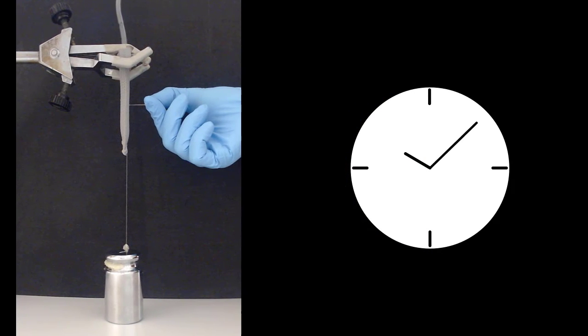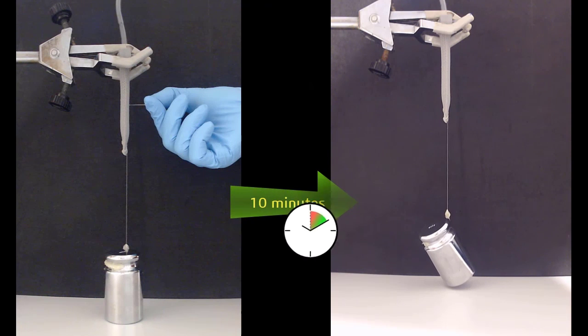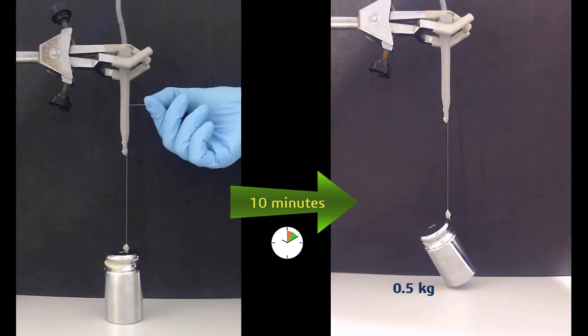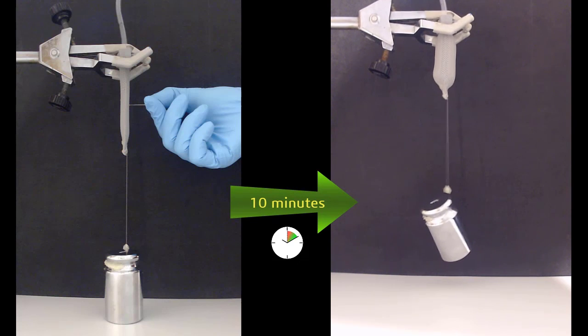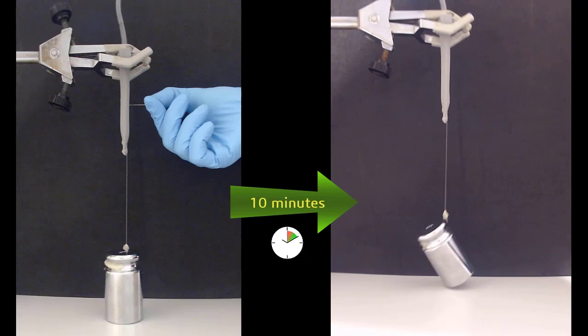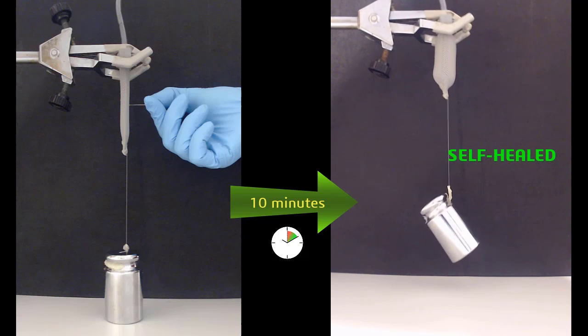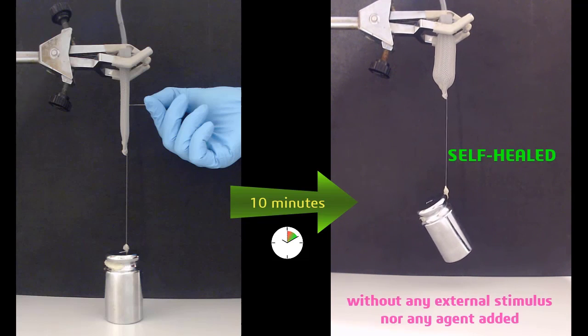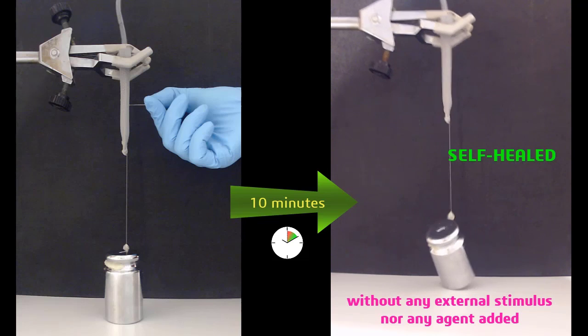To sum up, we have used our hydrogel to build a McKibben muscle which benefits from the self-healing capabilities of this hydrogel. After being damaged, the muscle can perform properly, as you are watching right now, even after only 10 minutes, thanks to the self-healing without any external agent or stimulus.